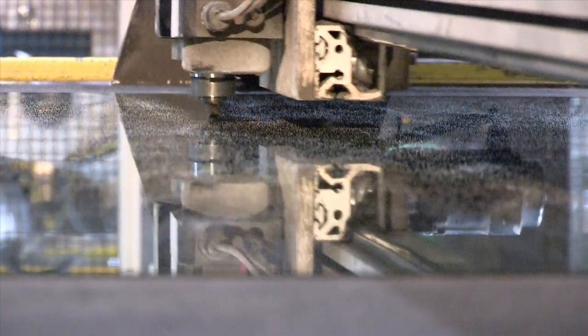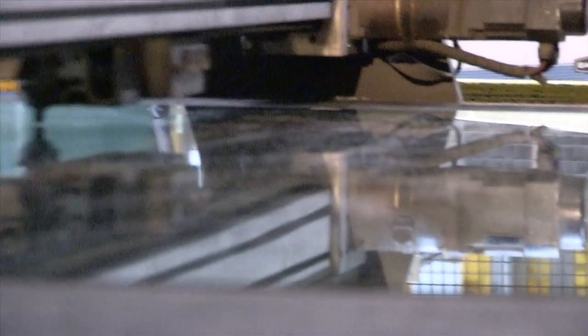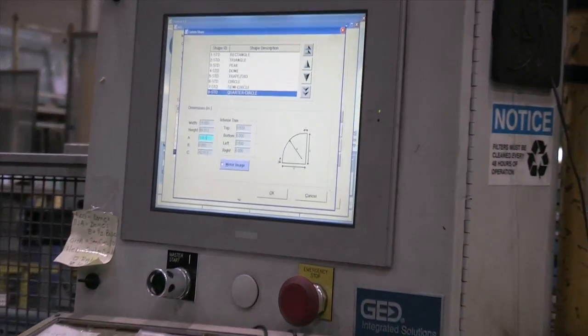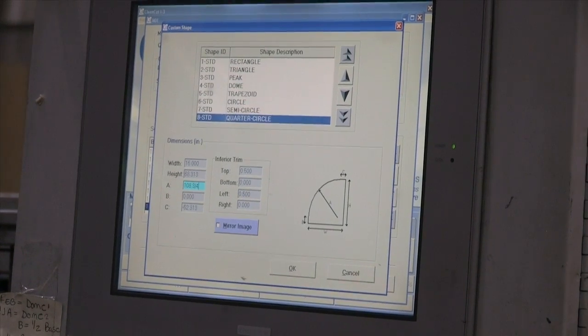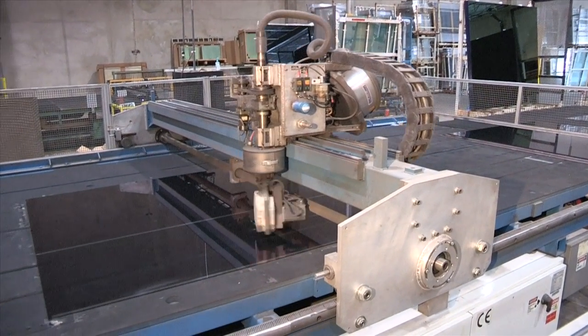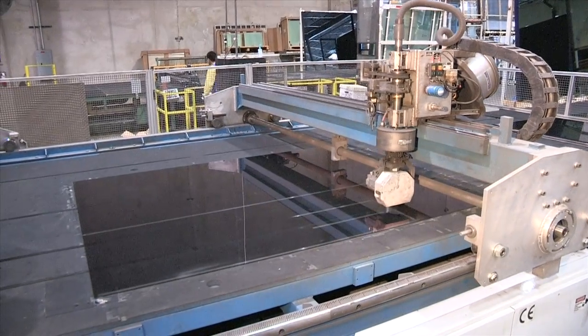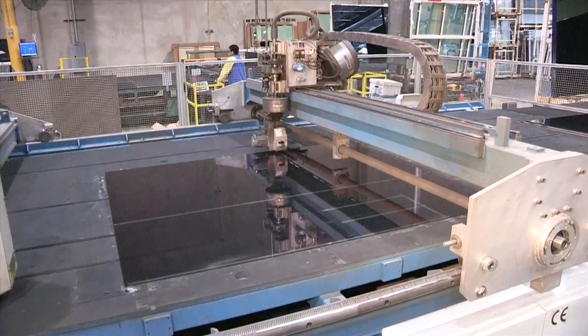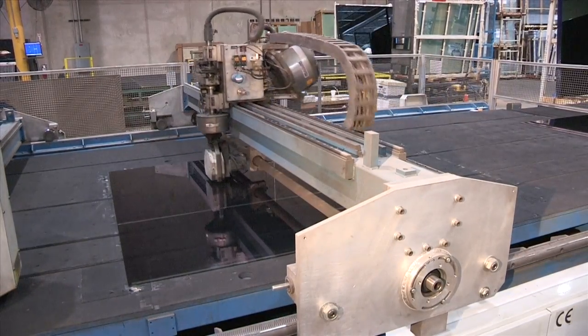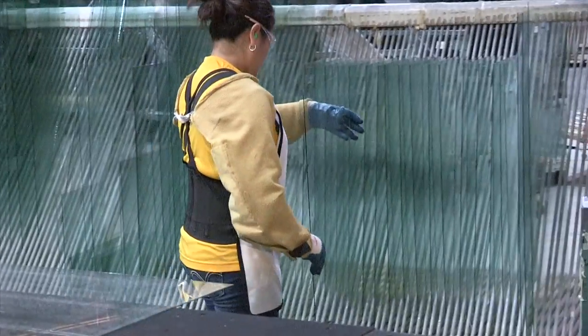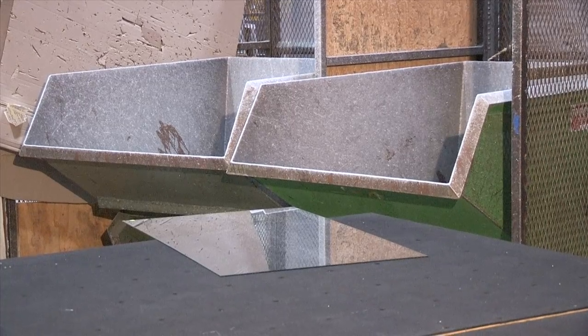The glass is scored using one of two computer-controlled optimizer tables. The optimizer is used for special shapes and uncommon-sized windows. A computer calculates the scheduled sizes for 1 week's worth of production and chooses how many pieces can optimally be cut out of each single larger sheet called a billet, thus reducing waste. The same machine uses a separate apparatus to shave off excess LowE to ensure a proper sealing of the insulated glass unit. After the glass has been scored, we separate the usable piece from scrap. The scrap is then recycled.